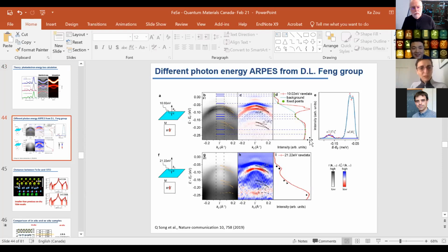Yeah, people actually did that. So the TC is already optimized. Potassium can only dope electrons. They've been able to add a little bit more electrons and the TC kind of flattens out, and if they add more, then TC actually goes down. There are also a lot of issues. There are theory proposals showing that potassium actually bonds to iron selenide. So in some sense, that doping is not clean at all. It might change the iron selenide band structure and the lattice structure completely by bonding the potassium to the iron selenide. So I won't trust it completely as a clean way to dope samples.